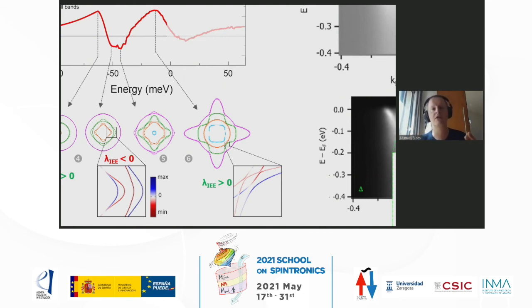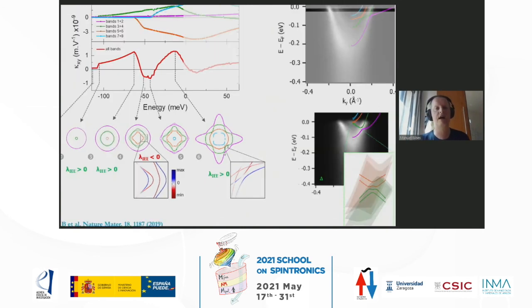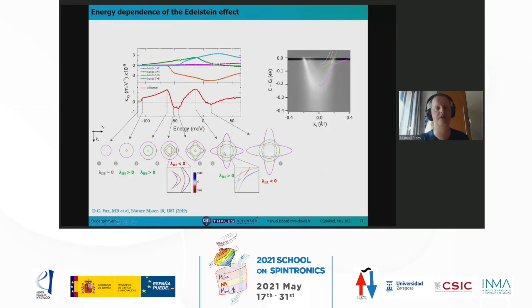So that's why in principle, it's better to work with topological insulators because you just have one contour. You don't have the other one which is compensating. And if you work with Rashba, you want to have a large Rashba coefficient, meaning that the inner contour is very small compared to the outer contour. So there's little compensation. But another way to limit the compensation is to work at points where the spin expectation values are not the same. And this is, I think, a very interesting feature. And this tells you also about the richness of the band structure of these 2DEGs.